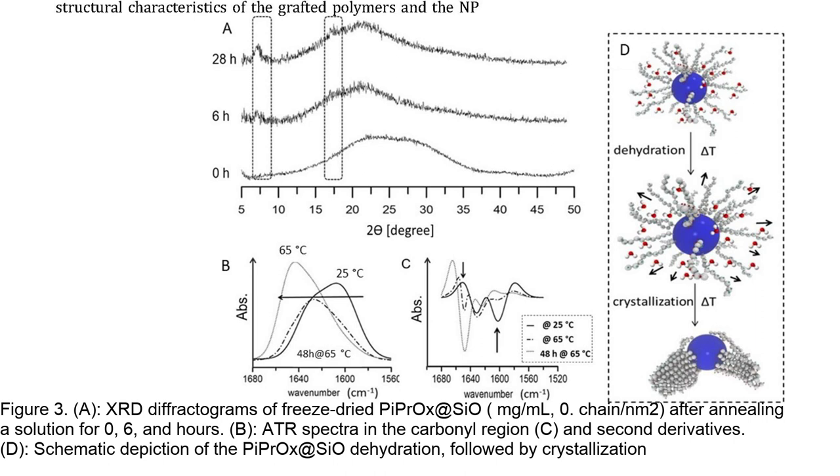The figure suggests that the self-assembly process proceeds through two steps: the rapid formation of amorphous aggregates via gelation mediated by the interaction between nanoparticles through the grafted polymers, followed by the slow radial growth of fibers via directional crystallization. Overall, Figure 3 emphasizes the importance of ligand properties, such as grafting density, in the self-assembly of hybrid nanoparticles and provides insights into the formation of complex hybrid nanostructures.